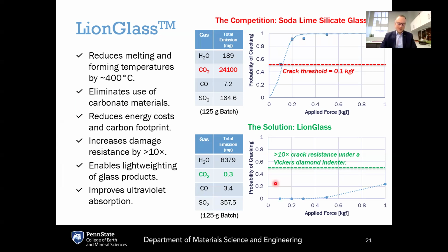This is something that we were able to do at Corning with some of the newer Gorilla glasses, where it was commercialized as native damage resistance. Here we're getting this improvement without ion exchange. It is a native property of the glass itself, where basically it's able to dissipate energy through kind of a nanoscale plastic deformation rather than dissipating energy by forming cracks. And so as a result, it takes a much larger force to be able to introduce cracks.